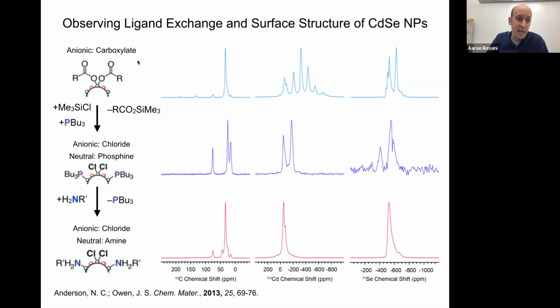The reason that nanoparticle chemists do this is because you initially synthesize your particles using carboxylate ligands during the colloidal synthesis step, but these are not very good ligands for the particles. They tend to dissociate. You tend to get a lot of undercoordinated atoms, and when you first synthesize your particles, you don't get very good optical properties. So if you want to improve the optical properties, you can go through these ligand exchange reactions, put on chloride surface ligands and neutral phosphines, or you can change out the neutral phosphines for neutral amines. These are even better surface ligands. And so these particles will have much better emission and absorption properties.